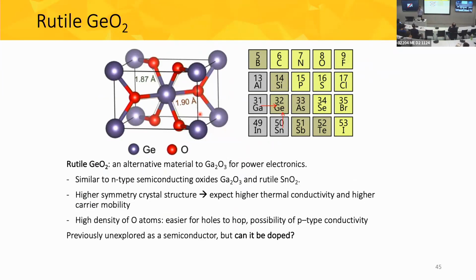You can go to higher orders in phonons. Phonons primarily give you momentum, not so much energy. So I would expect it to be important only in a very narrow energy region where one phonon does not give you enough energy to make it across the bandgap. But as soon as you have one phonon, that probably gives you any momentum you may need to create a transition across the Brillouin zone. What I think will be more interesting to look at is actually when you have multiple phonons. That's something we're currently investigating.